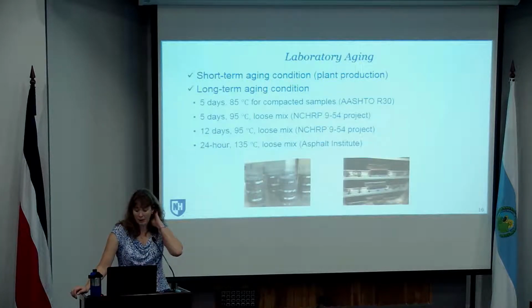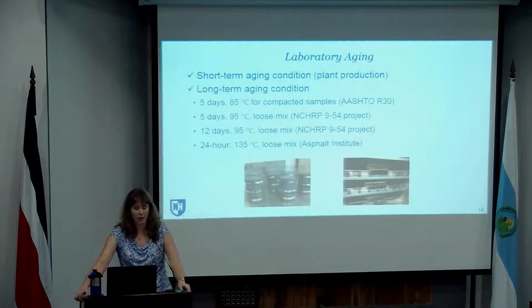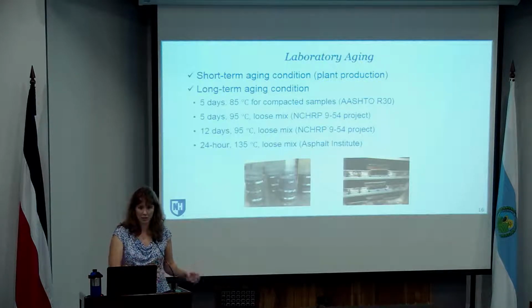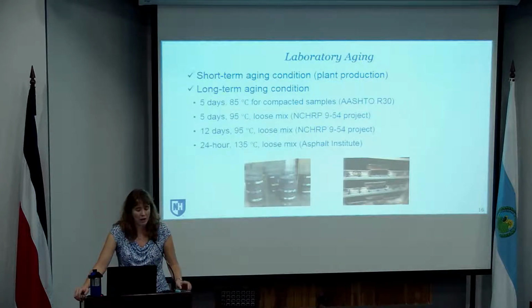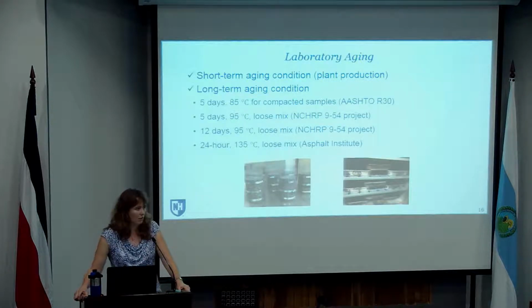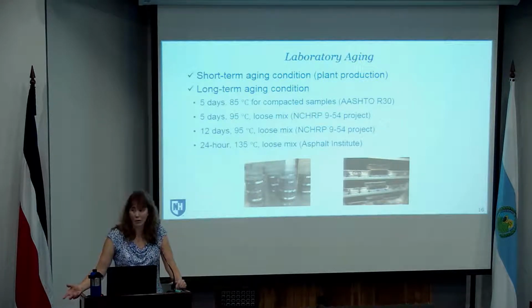Okay, so a little bit about the laboratory aging that we're using for these projects. For the short-term aging condition, we're looking at plant production. Okay, so when we did the laboratory versus the plant, we've got the laboratory-generated specimens that are short-term oven-aged, and then comparing them to those materials that are coming directly out of a plant. For the second project, for the long-term aging conditions, we looked at several different approaches that have been proposed recently in terms of representing aging that happens in the field over time.